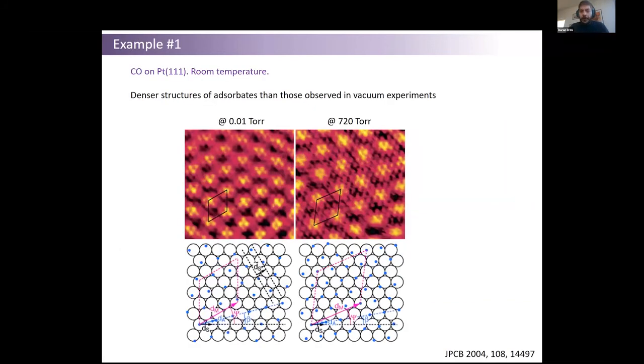Now, I'm going to show 4 examples, which I personally think are very important historically and for really better understanding of what's going on at ambient pressures. The first example is from Flemming Besenbacher's group from the Aarhus University in Denmark. It's on carbon monoxide adsorption on the platinum 111 surface. Carbon monoxide and platinum, this material system is the Drosophila of surface science. Maybe half of the surface science studies in the literature were done with either carbon monoxide or platinum.